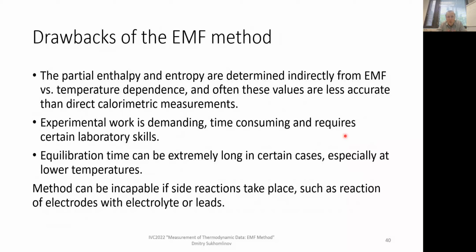For enthalpies and entropies of reactions, EMF might not be the most accurate method because we do measure them, but indirectly. We directly measure delta G values and then from the slope and from the intercept, we can find out enthalpy and entropy values. But usually these values determined by EMF are in good agreement with calorimetry, but still calorimetry is believed to be superior.